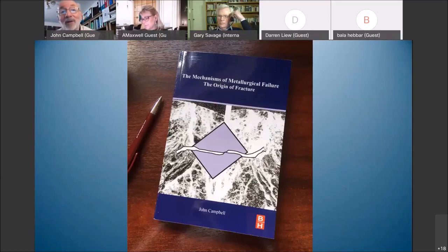I don't really want to get into that now, but that's because they've got liquid surface oxides. So when you fold over these surfaces, it's liquid oxide to liquid oxide, and now you don't form bifilms, you just form liquid droplets of oxide. So what is it? Trying to think of it, it's the high manganese steels, which are very successful, together with the high boron steels. These are the steels which seem to benefit enormously from liquefying the surface oxide. But Hadfield steels, is that what you were looking for? No, this is a new steel. It'll come to me in a bit.